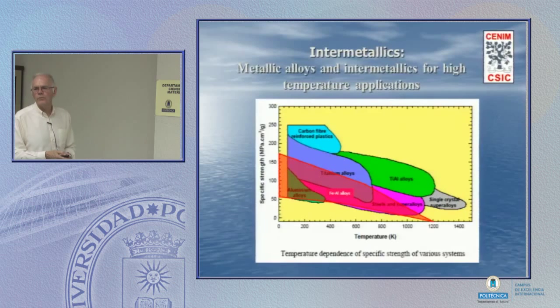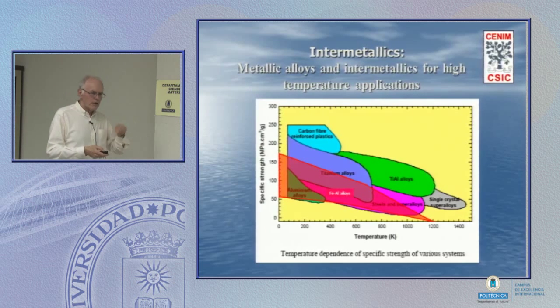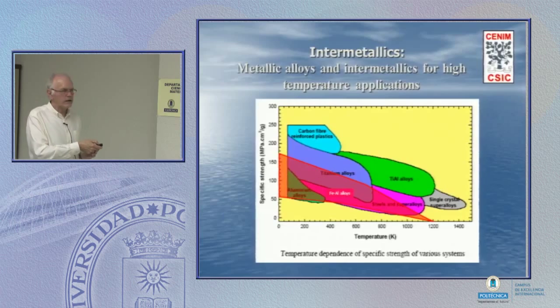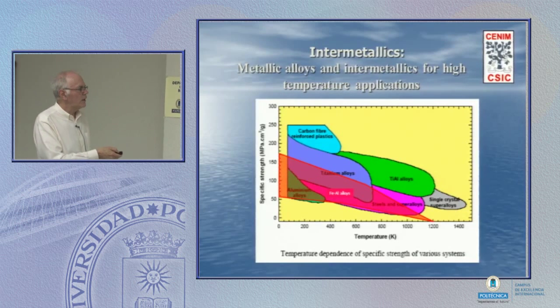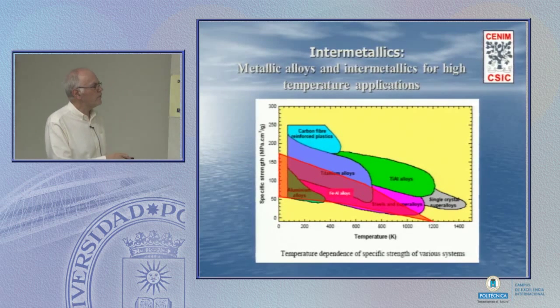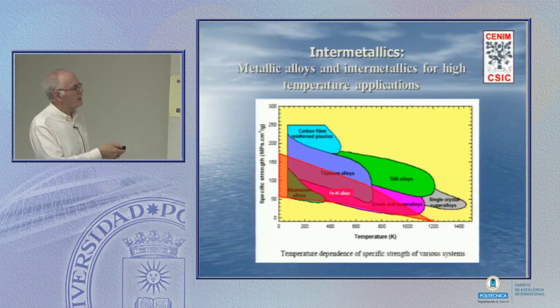Now, what are the materials that we're using for high temperature structural applications? Specific strength is typically more important. If you're rotating a turbine, it's the density that plays a role as well as the speed at which you're turning. If you're flying, again, weight is important. So specific strength we're looking at here, strength divided by density, and depending on the operating temperature. This is where the titanium alloys are found, here the high temperature single crystal superalloys.